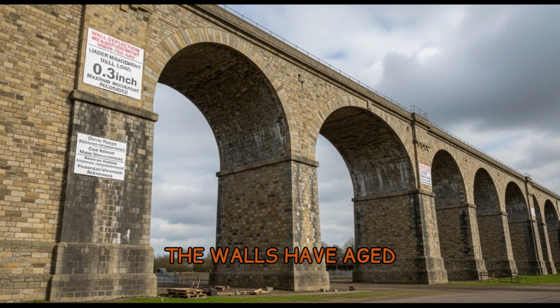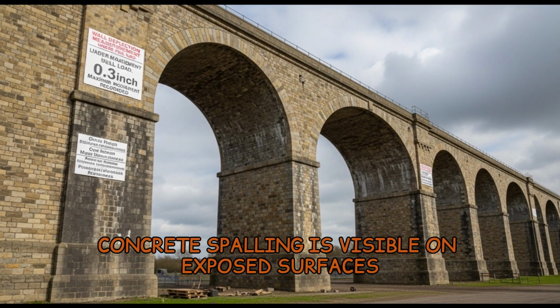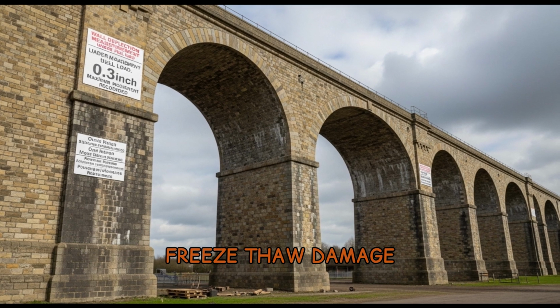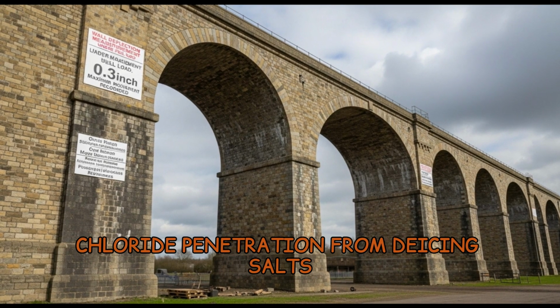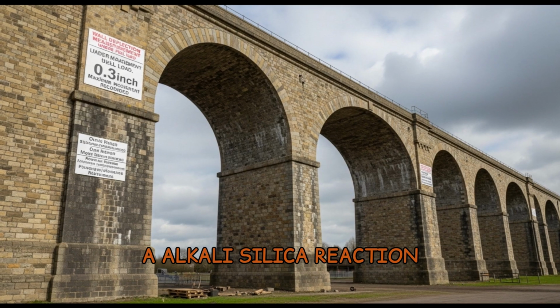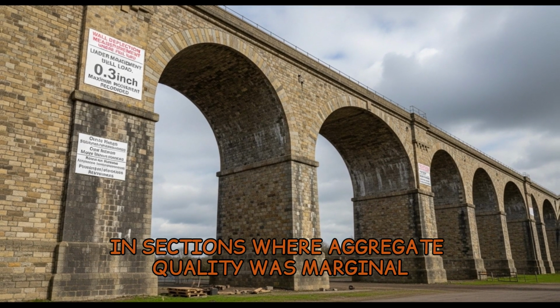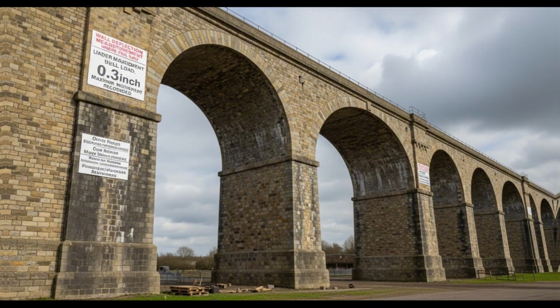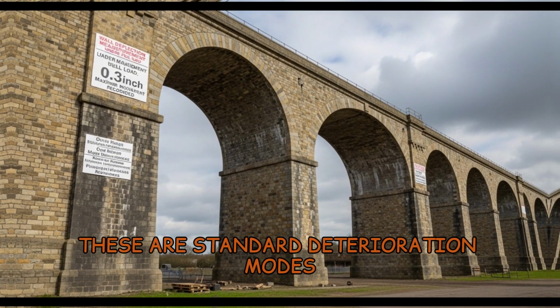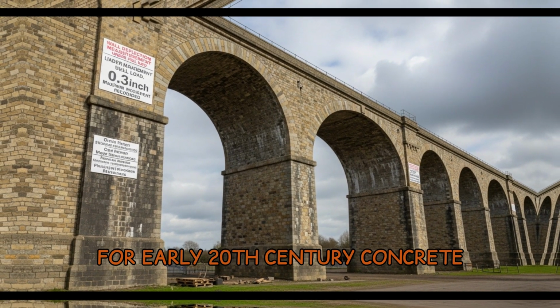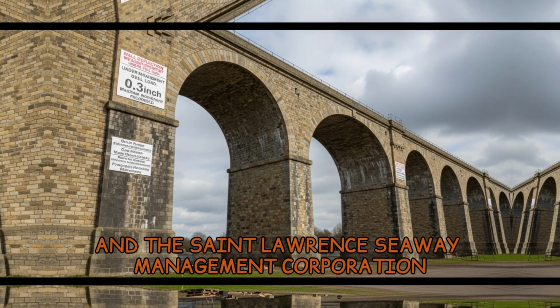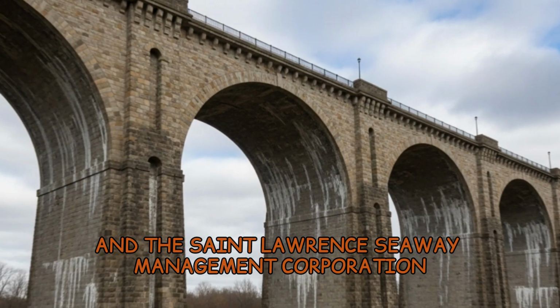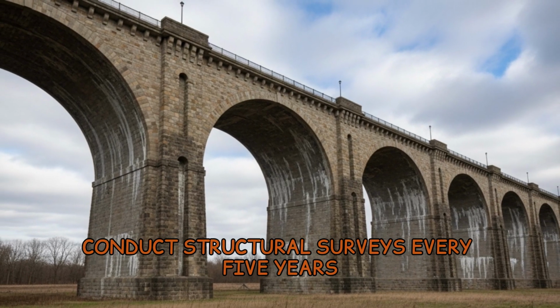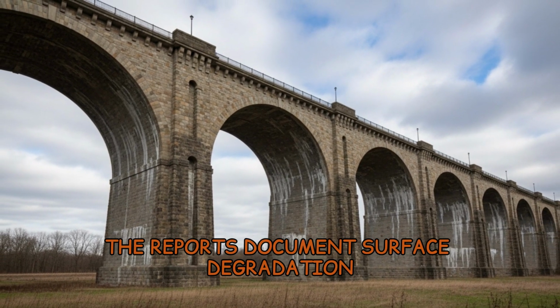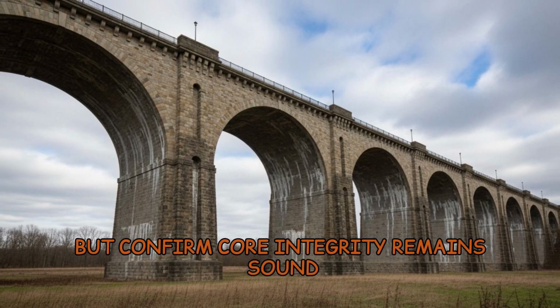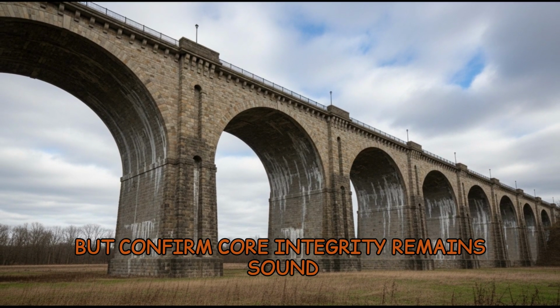The walls have aged. Concrete spalling is visible on exposed surfaces. Freeze-thaw damage, chloride penetration from deicing salts, and alkali-silica reaction in sections where aggregate quality was marginal. These are standard deterioration modes for early 20th century concrete. Parks Canada and the St. Lawrence Seaway Management Corporation conduct structural surveys every 5 years. The reports document surface degradation, but confirm core integrity remains sound.